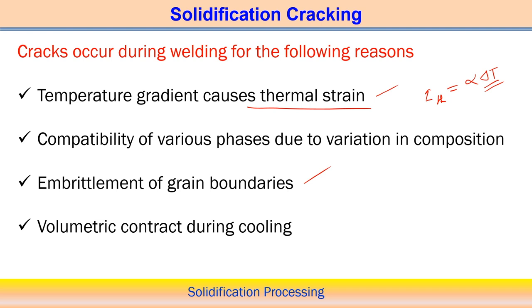Then the other point is the volumetric contraction during the cooling process. There is a shrinkage volume associated with this, and there might be different phases, and the shrinkage volumes of the different phases are different. That creates some kind of induced stress, and finally it is associated with the formation of cracks during the solidification process.